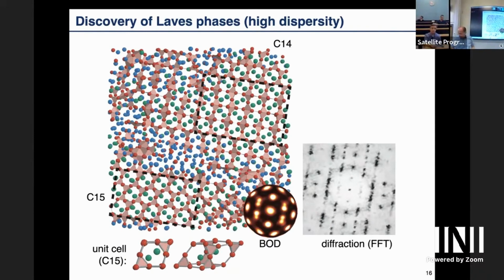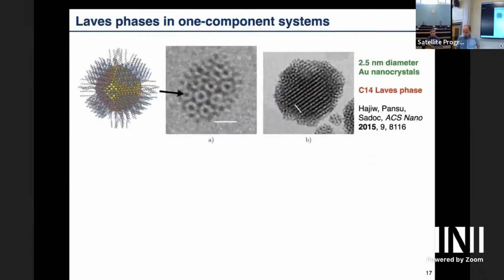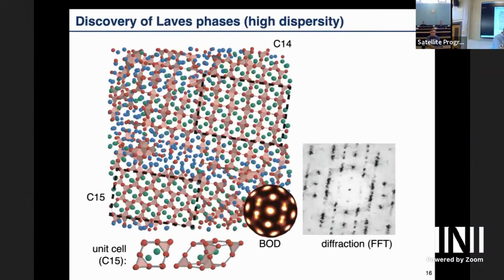So we see both of these Laves phases in there, and we don't know which one is more stable, but they form at very high polydispersity. And again, the high coordinations, so 16, are typically occupied by the large particles, and the low coordination red are occupied by the small particles. And then there is some mass here. We don't yet know if all the particles that are in the middle get pushed here, but that's one possibility. But at least that's what we got so far. Well, this is at least a possibility.